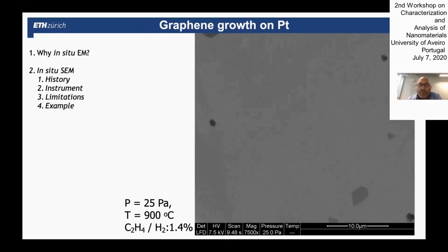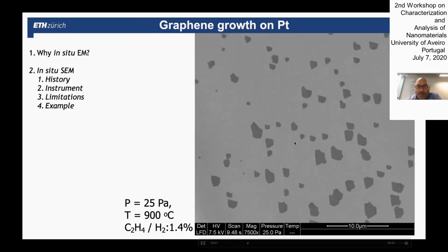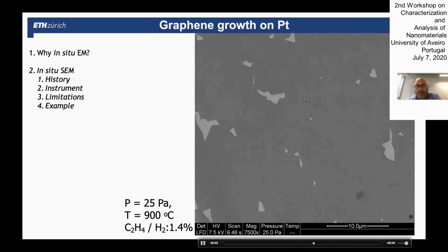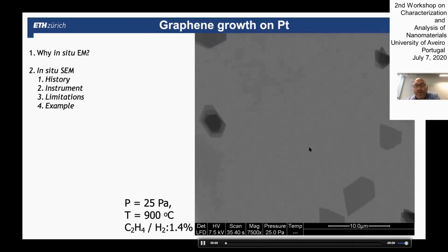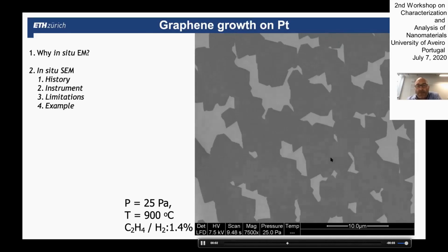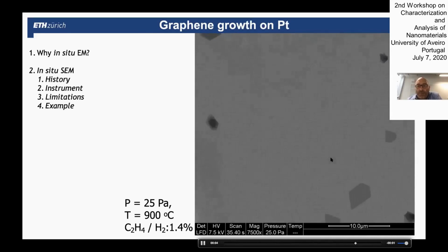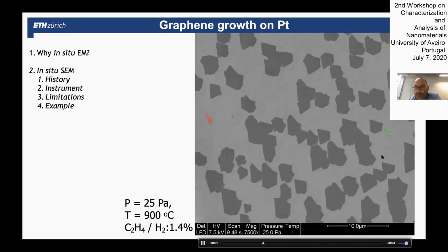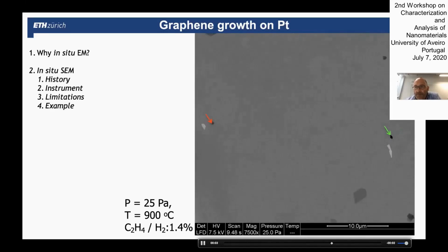What you see in this video is the growth of graphene. The first gray level that you see is a monolayer of graphene. You see how different islands form, and then there's a coalescence into a monolayer film. At some places, indicated here with arrows, you see the nucleation of a second contrast regime. There's a bit darker contrast, that's the second layer.